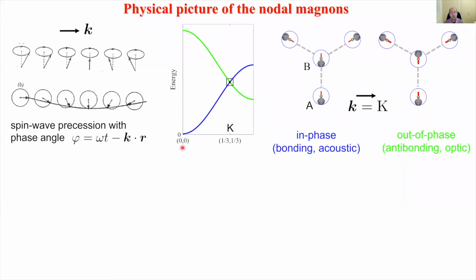So if we refer this picture now to the dispersion relations for the honeycomb lattice, and we focus at the corner of the Brillouin zone, this particular touching point here, and if we take a section of the honeycomb, just consider one spin on the A sublattice. This is an orientation at a particular time, looking from above. So the equilibrium direction comes out of the page, and this is now the tilted spin in a spin wave. Now, the other spins on the A sublattice have a phase that's directly related to the magnitude of this wave vector. And then at this particular K point, the angle is 120 degrees.